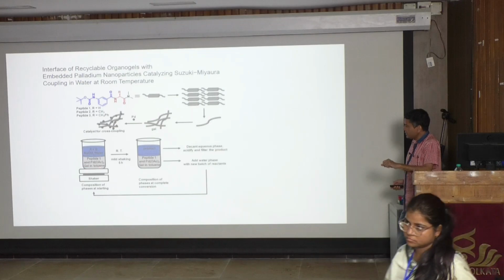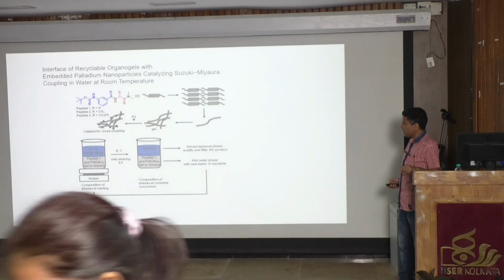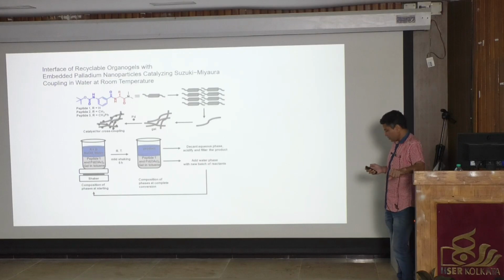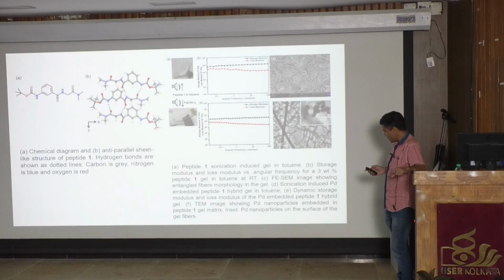Now, if the gel is there and on top of it is an aqueous layer, we cannot use a magnetic stirrer. So we have to let the whole reaction system sit. After the reaction at room temperature, in a mild setting for 5 hours, the product will form. Then we just decant the aqueous layer from the top of the organic layer, from the top of the gel. Again we fill up the aqueous layer with the reagent, and that cycle can be continued. So that is what we have planned.